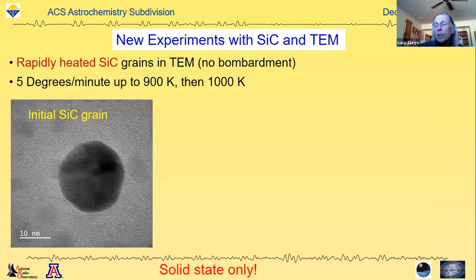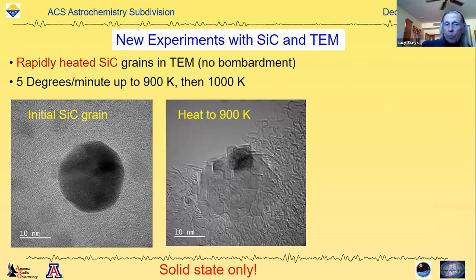And so we really believe that we can form C60 from heating silicon carbide grains. We actually did another experiment just a few weeks ago where we rapidly heated these analog grains with no ion bombardment. So here are some results. There's the initial silicon carbide grain. We rapidly heated it, 5 degrees per minute, up to 900 Kelvin.